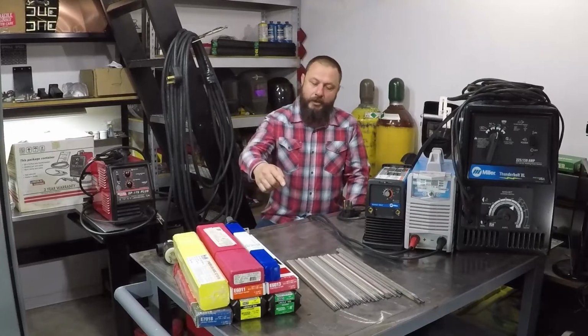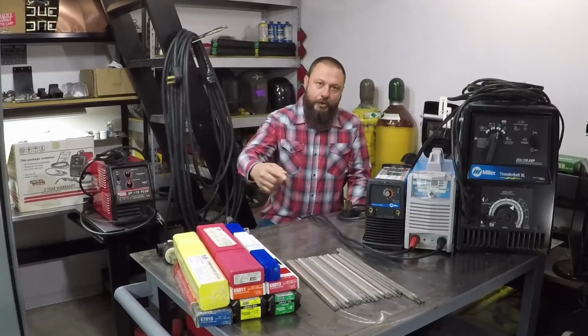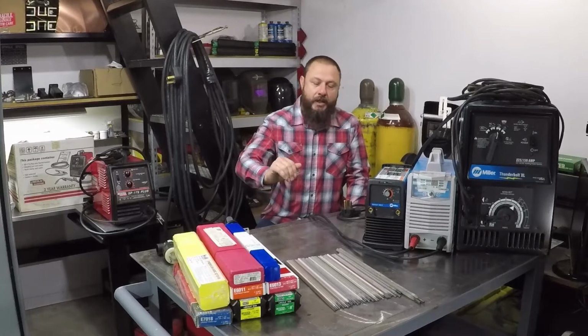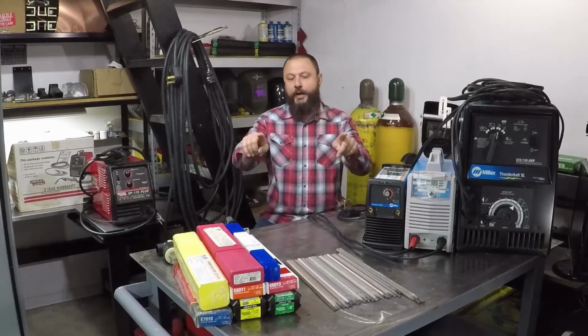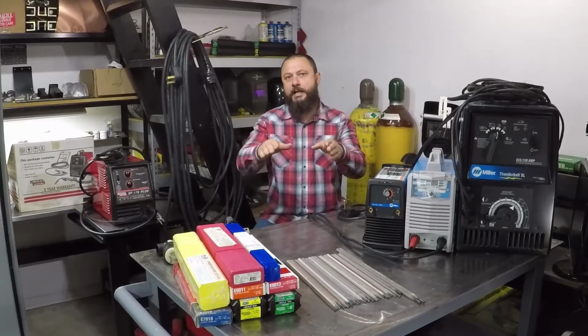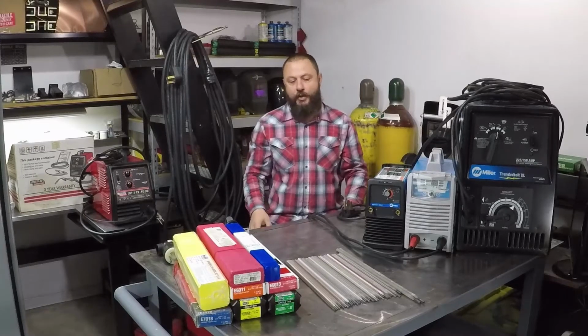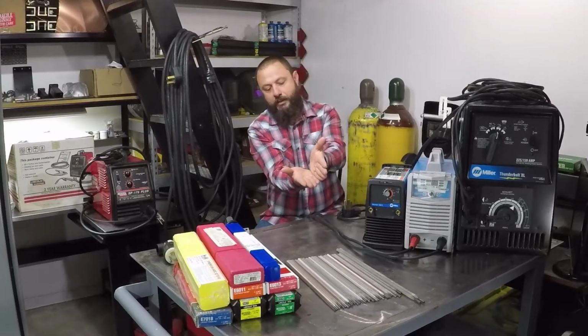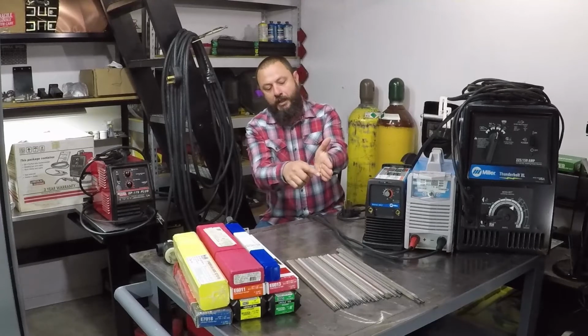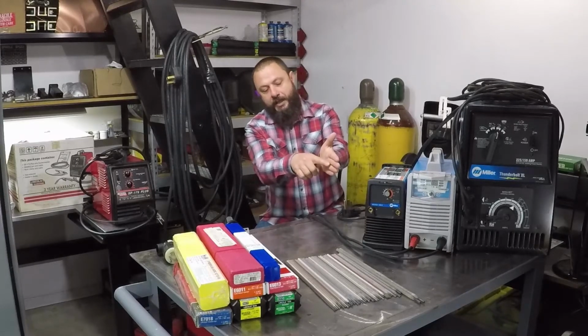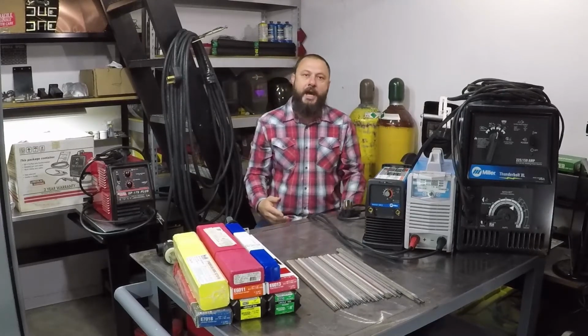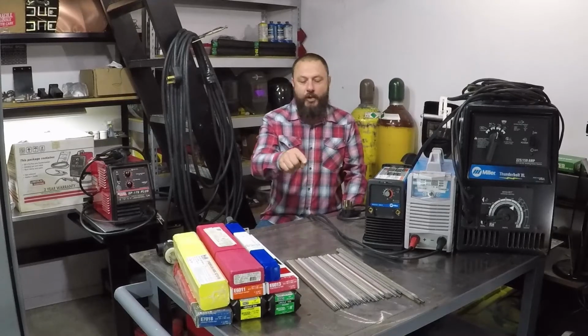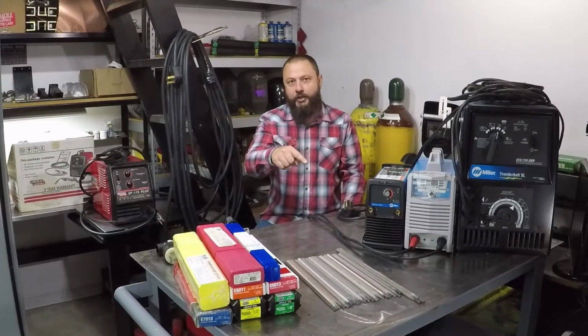Undercut. You weld. When you finish, you clean the slag, hit it with the wire brush, and you find craters at both sides of the weld bead. Or sometimes if you weld a T-joint, you find the crater at the top of the bead. This could happen because the current is set too high or you're not weaving the weld correctly.